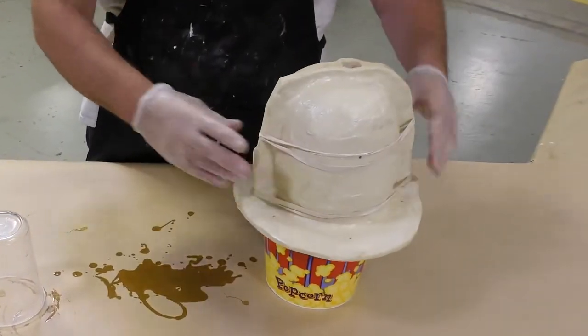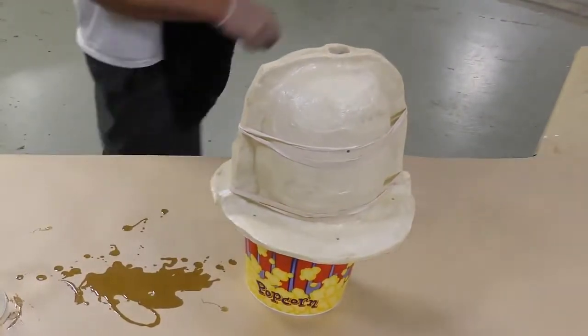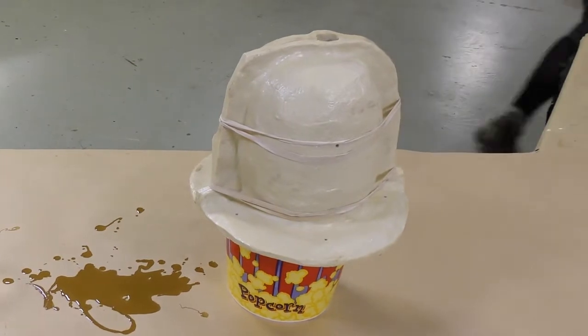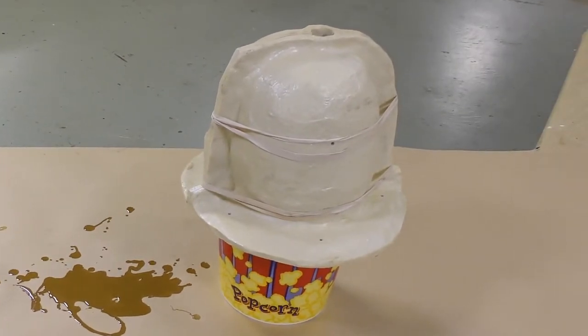Now, the handling time for the material is 90 minutes as prescribed by the technical bulletin. But since we applied several thin layers, I'm going to give it some extra time to cure. So instead of 90 minutes, we're going to allow it 2 hours to cure before demolding.